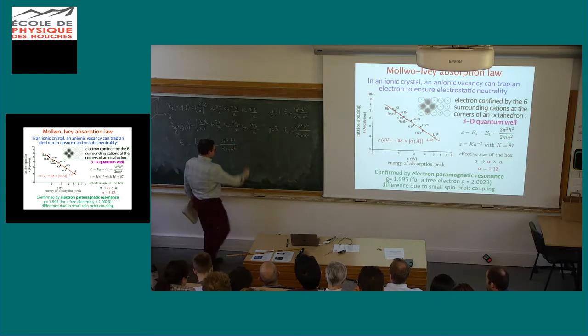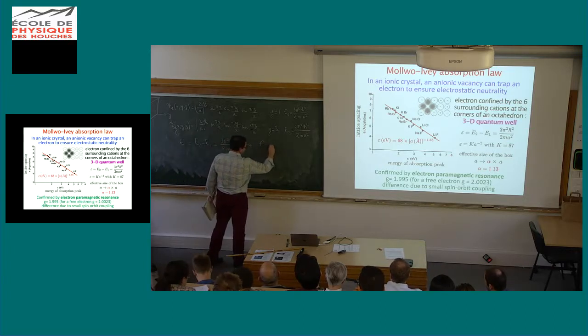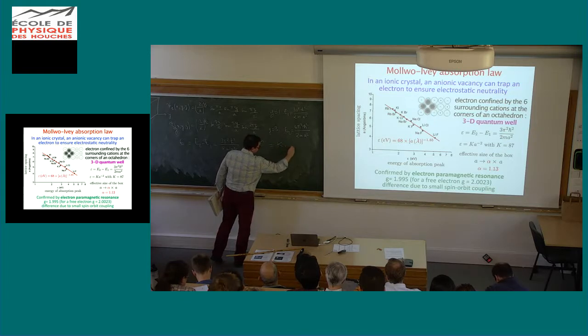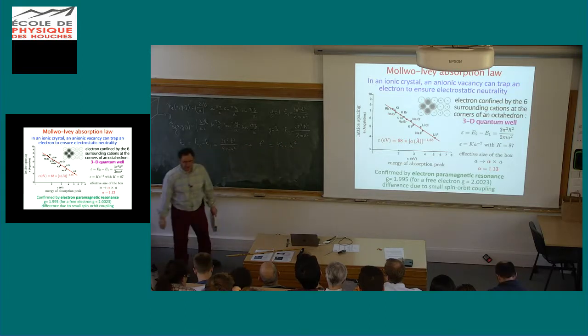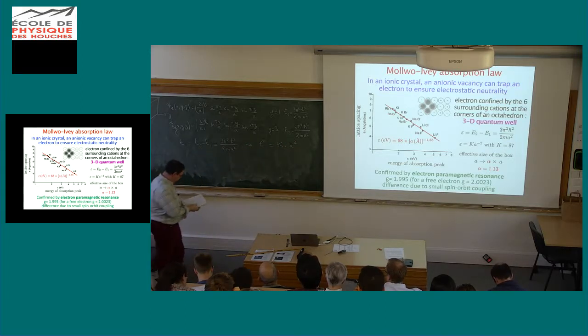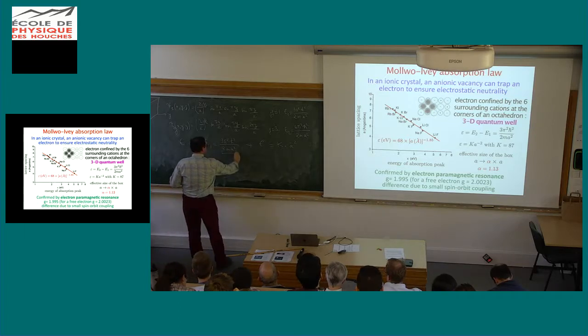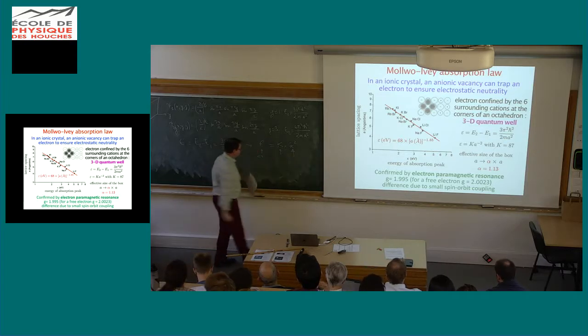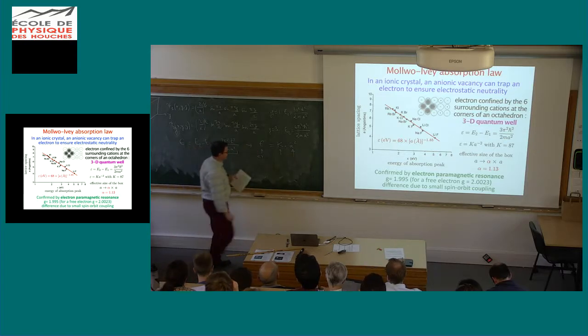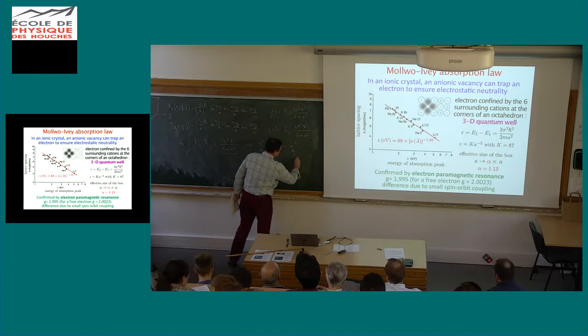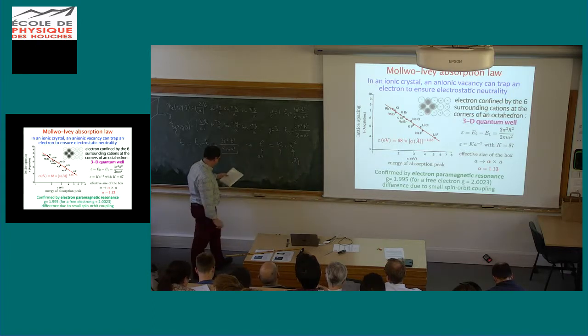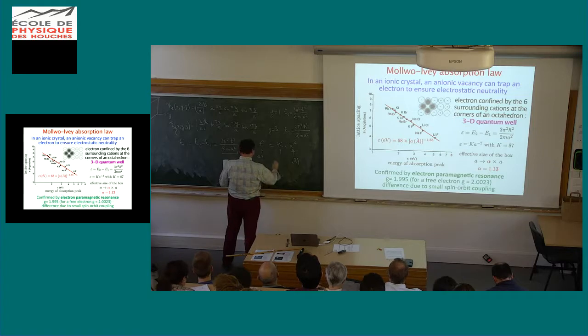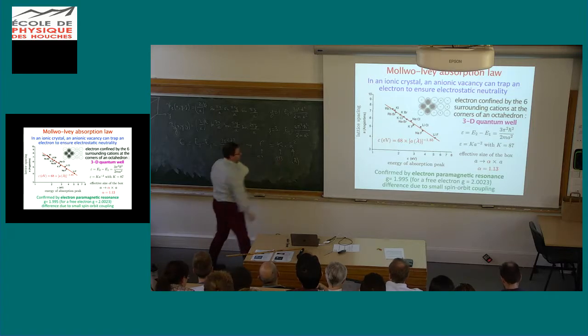So this is a law which tells us that the difference goes as 1 over a squared, and if I take the two parameters, expressing the difference of energy in electron volts and the lattice spacing in angstroms, this parameter, if you do the calculation, is 1 over 33.